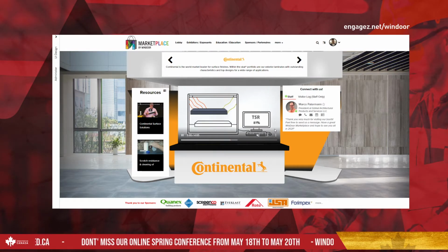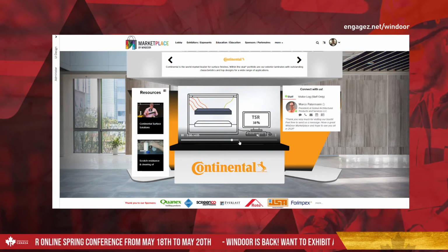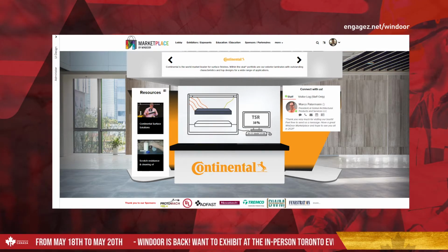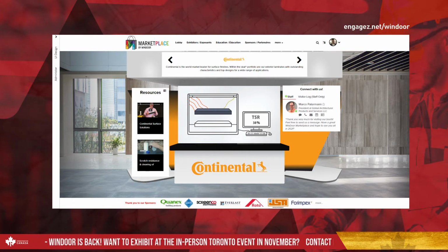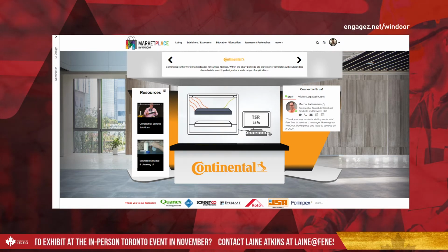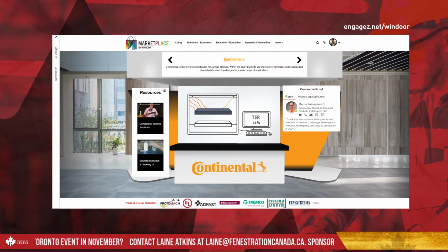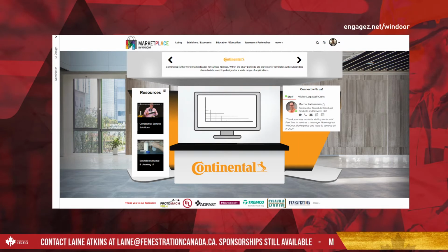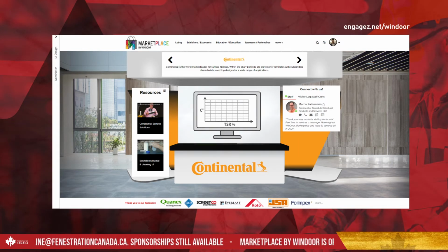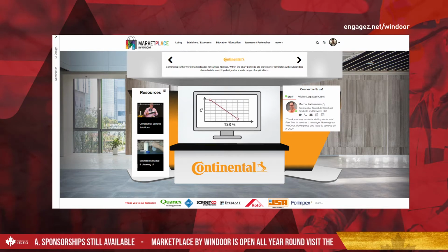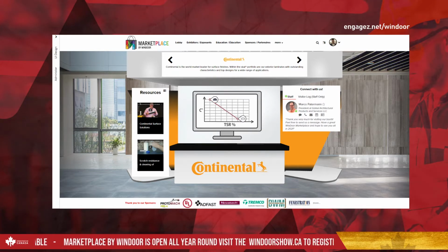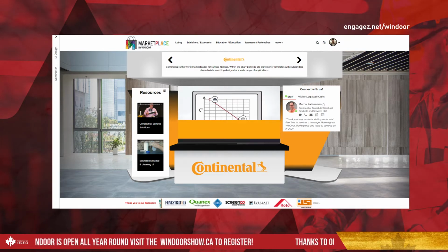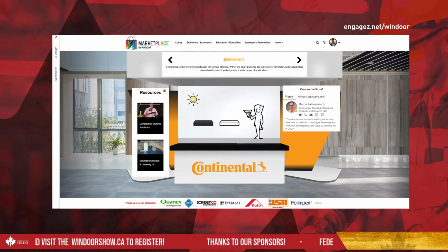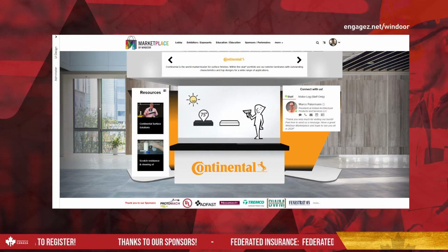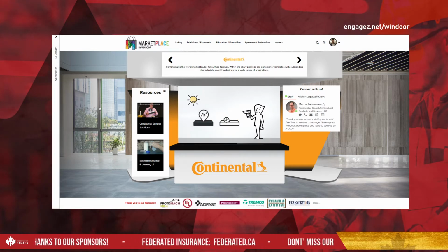What you see on our booth is basically one of the main technical aspects of the Cool Color and Cool Color Plus laminates of Continental. Continental has a patented formulation in their pigmentation for the laminates, which we call Cool Color Plus. These are highly reflective pigments in the infrared range of the sunlight to prevent and reduce the risk of warping of especially vinyl windows, because it reduces the heat buildup. What you see on the booth is the presentation of the TSR, total solar reflectance.